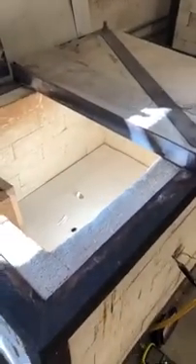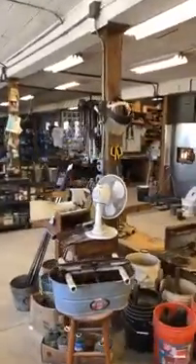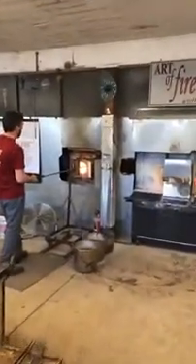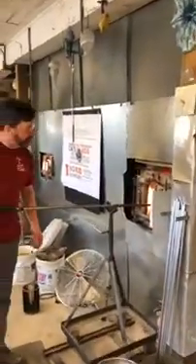Nothing in there? Okay. So what we'll do is throw open a door and let you take a look in. And that really is just a big box of bricks. But what we'll do is put a piece of glass in there, and for our glass, the critical range is between about 900 degrees and, let's call it, 750. Between those temperatures is when the glass, if it cools too quickly, stands the greatest chance of shattering. So by having this box of bricks and turning off the heat source at the end of the day, we're able to let it cool down gradually. That cooling process, the annealing, takes many hours. If we make really thick pieces of glass, it takes even longer, because the middle and the outer layers of the glass cool at different rates.